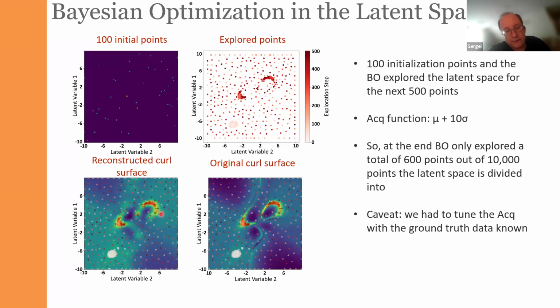So here you can see the original curl surface. That basically is the ground truth data and the Bayesian exploration on top of it. This is the reconstructed curl surface. This is how the Gaussian process thinks the curl is distributed. You can see that the reconstructed and the original are fairly close. But notice a very, very important thing, that in this case, the features on which the interesting behaviors are localized are kind of localized, but it's not like a simple maximum. It's a fairly complex manifold.